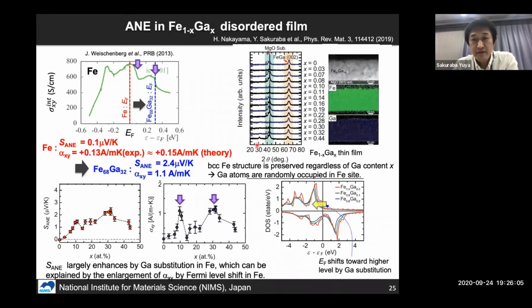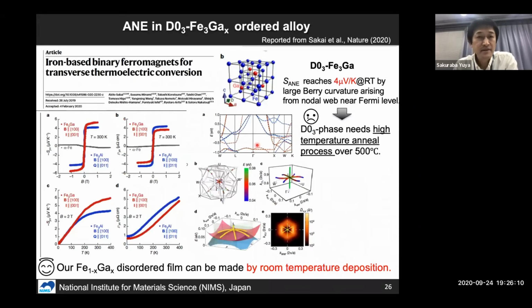Okay, so this is a result we reported last year, but as you may know, recently very impressive data was published in Nature. This is a paper from a Japanese group, Professor Nakatsuji's group. They found a very large anomalous Nernst effect of 4 microvolt per Kelvin in DO3-ordered Fe3Ga. They explained that the origin of this anomalous Nernst effect is the large Berry curvature arising from the nodal web around the Fermi level.